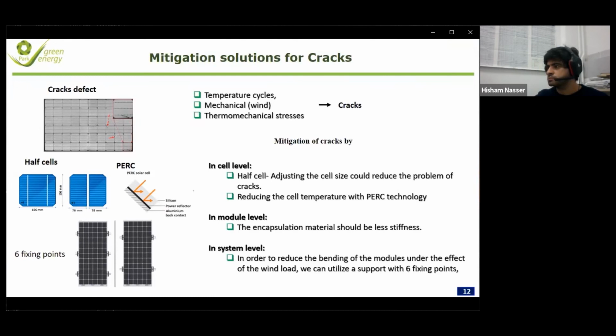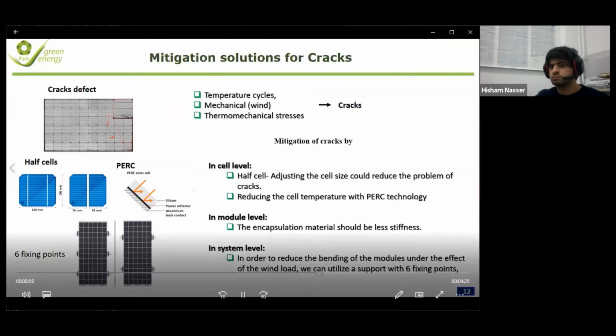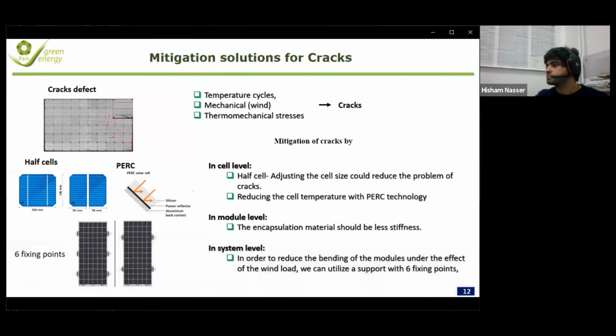At the module level, using an encapsulation material with less stiffness should improve the mechanical protection of the PV module. And at the system level, we recommend using 6 fixing points rather than 4 fixing points on the PV module in order to reduce the bending of the PV module under the effect of wind load.